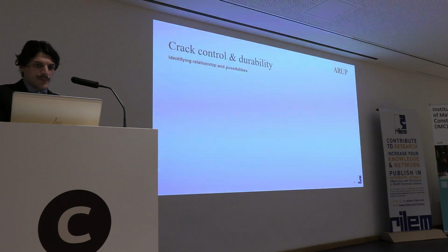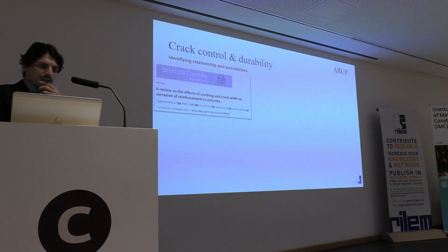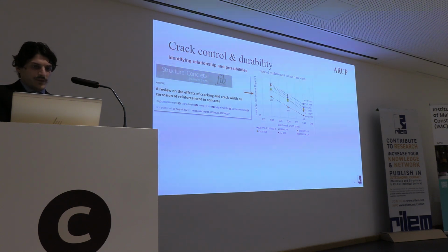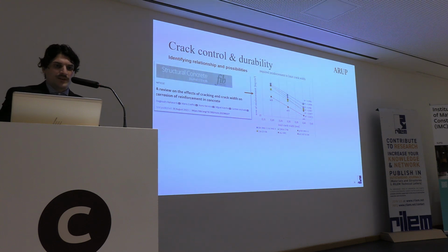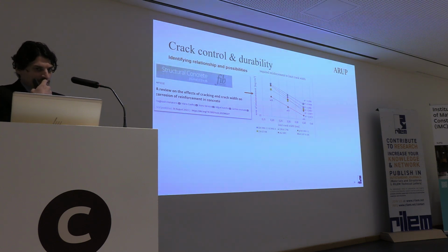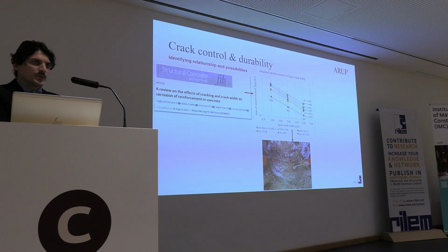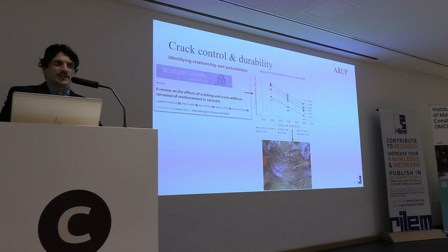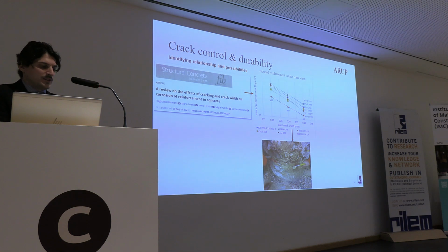And that led us to really revisiting some of the assumptions that we're making when we're imposing crack width limits. And through working with other RILEM members like Cameron and Rada, we mentioned previously that cracking is actually very well correlated with rebar quantity. But we've seen some problems with adding too much reinforcement for crack control. This is a problem in a pile that was constructed relatively recently with over-reinforcement because of crack control, and concrete couldn't flow, so the durability was compromised. So, we were going for good crack width control, but in the end, we ended up with compromised durability and sustainability of the element.